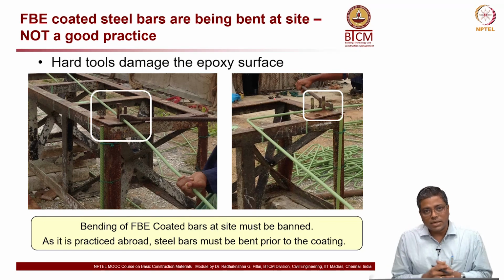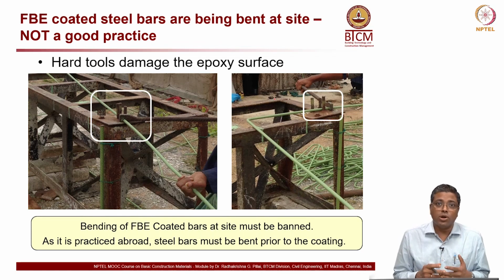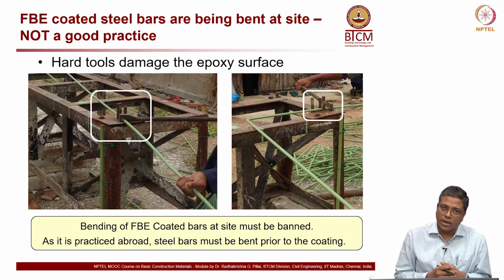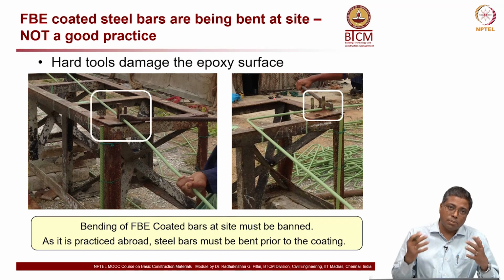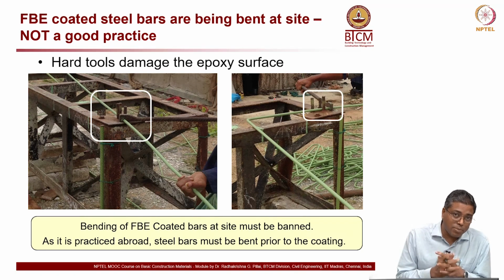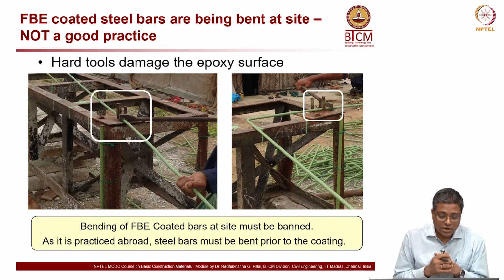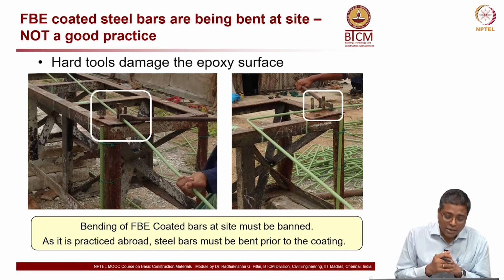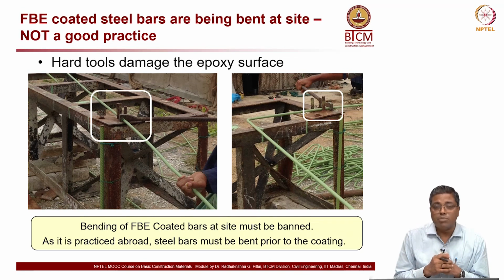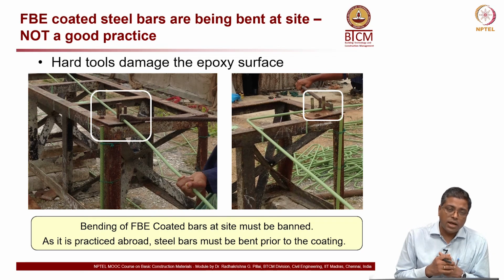And what do you do? You will bend these rebars. Ideally speaking, you are not supposed to bend it after applying the epoxy coating. Abroad, you will see that the bars are bent first and then they are epoxy coated, but unfortunately in our country this is not the practice, even though it is recommended in the codes. But we see a lot of places like this. As you see in the photograph, we bend the bars after they are brought to the construction sites, which is not a good idea. It should not be practiced.